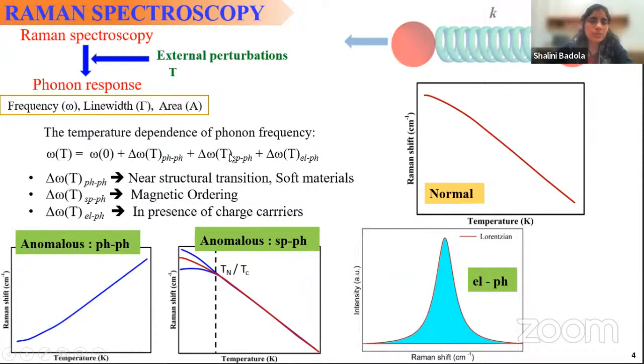Now suppose we consider a system which does not carry spin-phonon coupling or electron-phonon coupling. Spin-phonon coupling is present in magnetic materials. Electron-phonon coupling is usually found in semiconducting materials, or materials which can provide charge carriers to couple with phonons. And phonon-phonon interaction can appear in materials which are near a structural transition, or in materials which exhibit negative thermal expansion. The manifestation of phonon-phonon interaction in Raman spectroscopy can be seen as represented by this first schematic, where as we increase the temperature, the phonon frequency also increases, which is contrary to what is expected from the normal behavior.